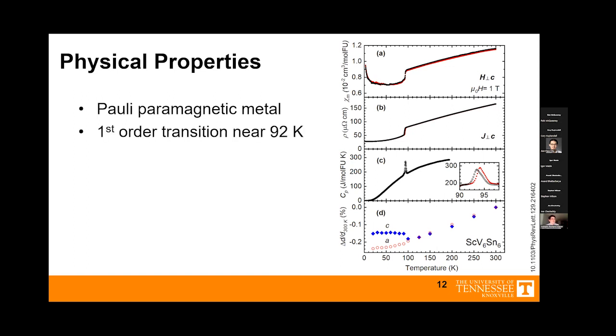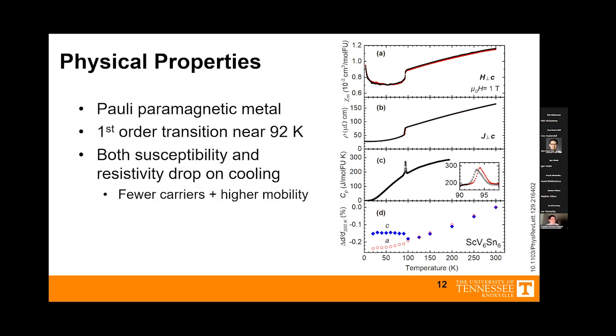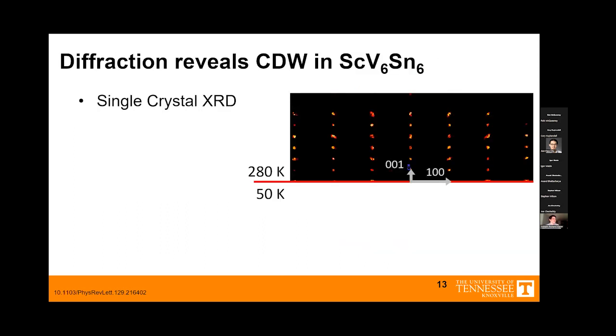It's first order. And strangely, as I mentioned, there's both a drop in the susceptibility and the resistivity, and that's odd. Most charge density waves see a jump up in resistance as a gap opens. So something's a little different here. The explanation, it turns out, is we do have fewer carriers, but they're just scattered less. And that decreased scattering leads to a drop in resistance.